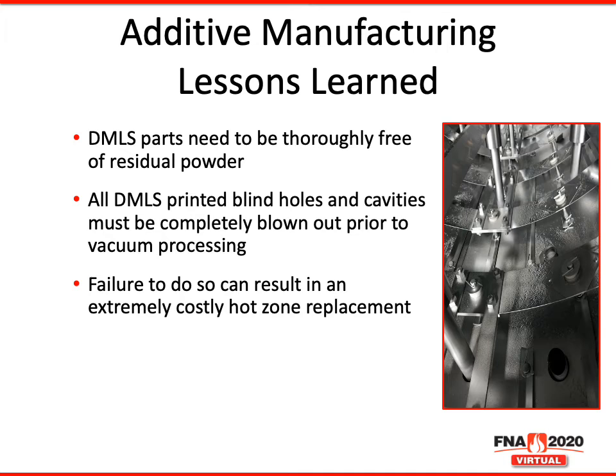In this picture, you can see where some of the powder has blown out of the part and has been deposited on the moly heating elements as well as the moly metal in the backing. Because of this, this hot zone had to be pulled apart and cleaned. So it's very important that these holes are free of any binder and powder prior to processing.